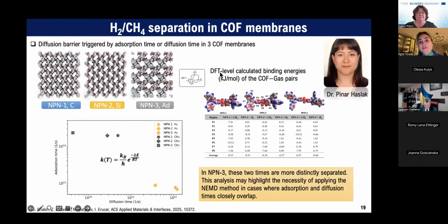Then we switch to electronic-based calculations, so DFT simulations. What we aim to do here is compute the binding energies of gas molecules with respect to this NPN family. We consider different orientations, and then we computed the binding energies. So here we propose a relationship. Let me show you. On the y-axis, you can see the adsorption time. This basically comes from the crude transition state approach. kT is the hopping rate, and we assume that it is the adsorption time. And here, delta E is the binding energy that we computed from the DFT simulations.